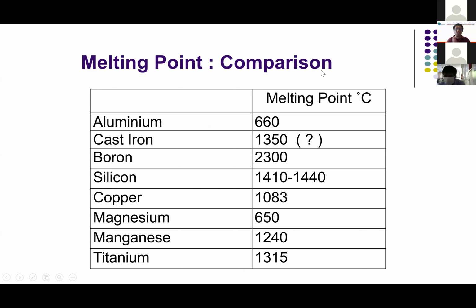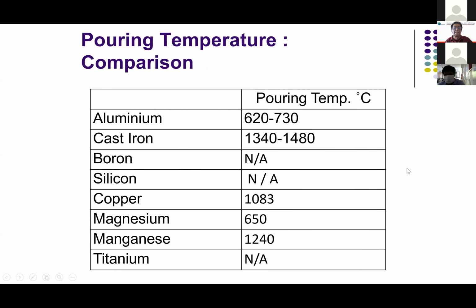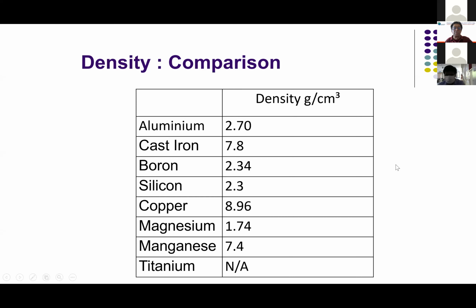Melting point comparison, just to give an idea. Aluminum melts at 660 degrees centigrade. Cast iron at 1350. Boron 2300. Silicon 1440. Copper 1083. Magnesium 650. Manganese 1240. And titanium 1315. Pouring temperature is again the same. We are comparing the density. Aluminum is 2.7, roughly one third of iron. That gives a major advantage over steel and iron. Boron is 2.3 and copper is 8.96, so copper is also a much heavier metal. Magnesium is of course lighter, 1.74.